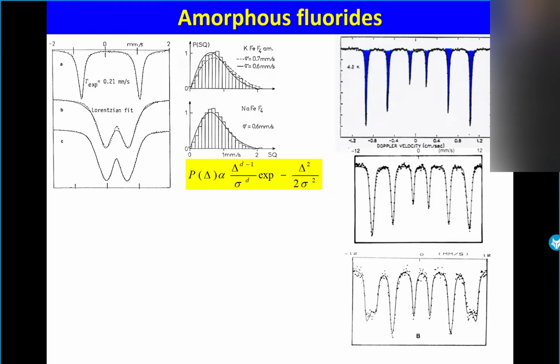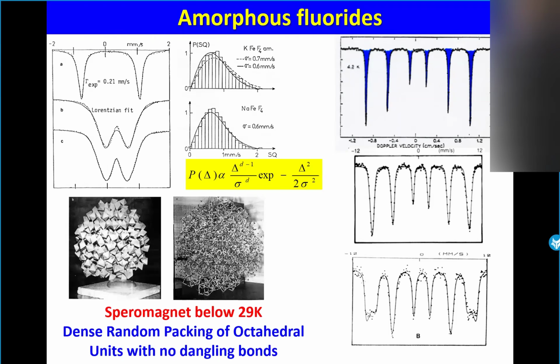So now we have the crystalline sample, as I showed you before, and the amorphous one. You can see the lines are broadened, rather symmetrical. And now we have to apply an external magnetic field. On applying an external magnetic field, we have a speromagnet, as I showed you before. That means you have a distribution of magnetic moments in the block magnetic state. And for this, we were able to develop some modeling by considering an assembly of octahedral units. Of course, if you consider the rings, you have 3, 4, 5, 6. The 3 and 5 rings give frustration of the ferromagnetic structure.